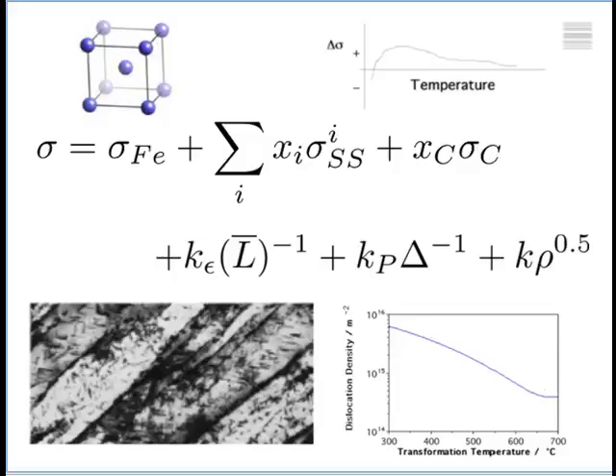You might notice that there are some dark particles in this image. Those particles are precipitates of cementite. And the larger the number density of those precipitates, that means total number of particles inside a given volume, the smaller will be the spacing between those particles, and therefore they will obstruct deformation more. And therefore, the strength increases as I decrease the spacing between the particles. So this is the spacing between the particles. And if I decrease the spacing, then the strength will increase.